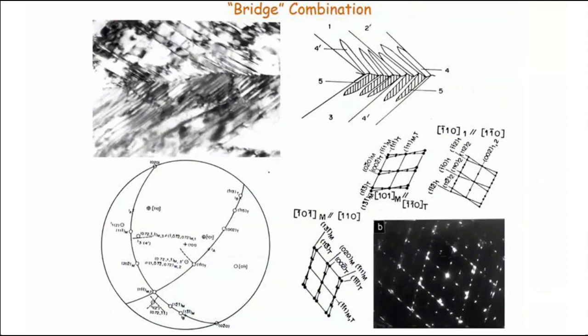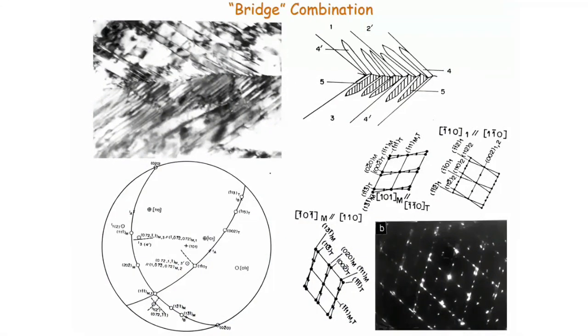All in all, I will just summarize this and say we started off with a contention that we have to have some kind of crystallographic restrictions imposed so that we can get the original variant back. The nickel titanium gives us the best examples of that, where there are these features which we have in a way guessed out what may be the case. We see several evidences of this happening within the microstructure, that these microstructural restrictions give rise to the reversibility.